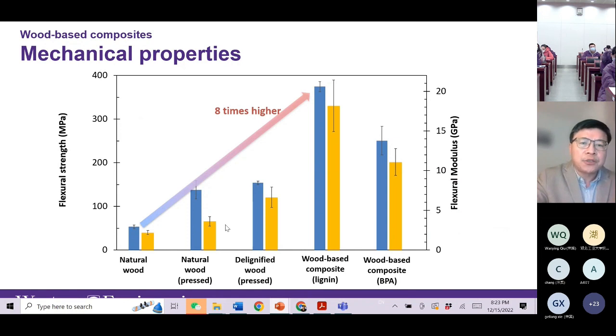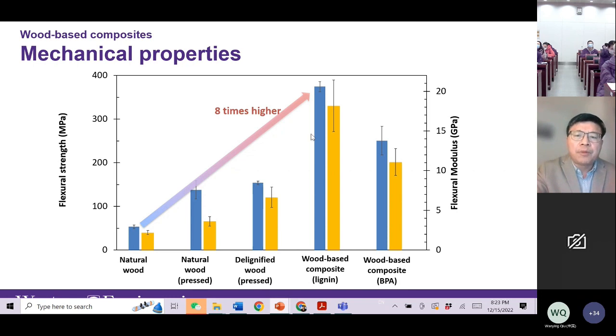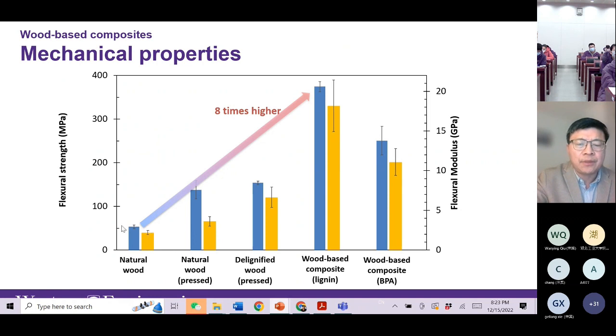And this slide shows the flexural strength. Flexural strength is the bending strength of the specimen. Our wood-based composite material with lignin gains almost 8 times higher flexural strength compared to natural wood. And compared to a wood-based composite using petroleum-based bisphenol A epoxy resin, our lignin-based composite actually achieves more flexural strength than the commercial epoxy-based composite.